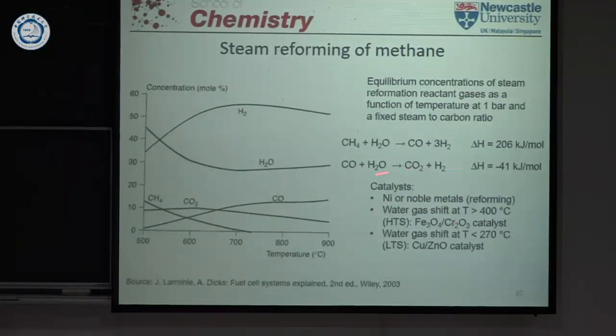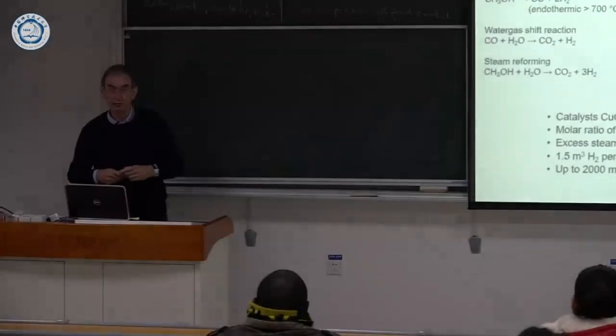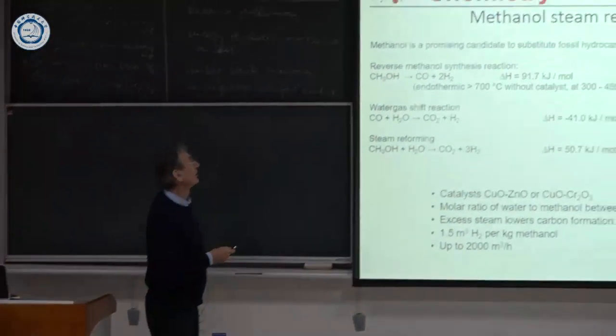And that's shown here, that for the different stages you need different kinds of catalyst. Nickel is typically a catalyst for the reforming, but for the gas shift reaction at high temperatures, you have a mixture of iron oxide and chromium oxide, and at lower temperatures you need a copper catalyst on a zinc oxide support, which is also a reforming catalyst for methanol. So it shows in the end everything works, but these are various stages you have to go through, and it's a bit complicated what needs to be done. But the industry is fairly well established, one has to say.